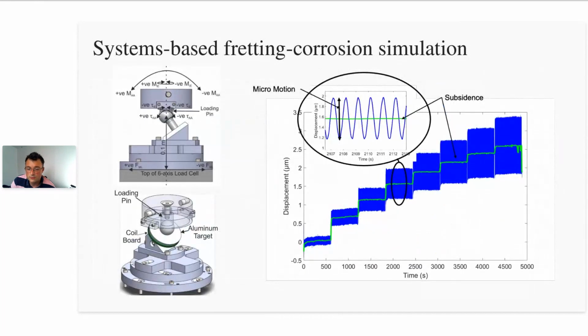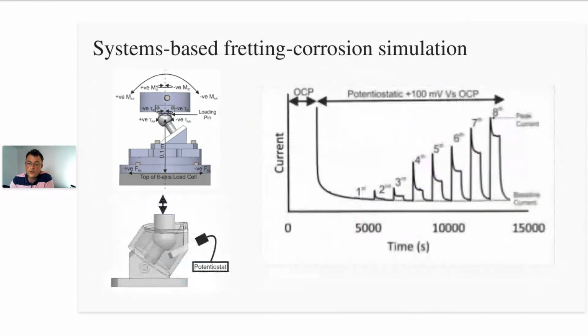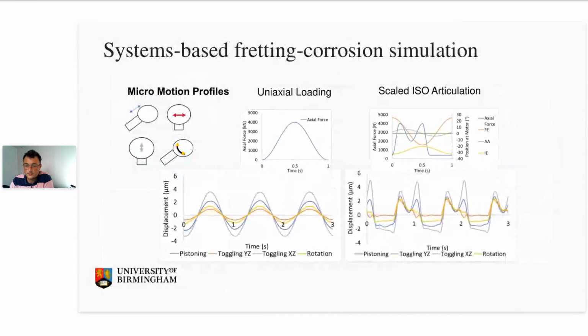But we can also then integrate sensors into here to then look at things like micromotion. So this is an eddy current-based micromotion sensing array where we can measure 3 points in the plane, look at toggling the micromotion. And also electrochemistry, and then ultimately merge the two together to give us information about what's happening at that interface, which you typically wouldn't get from standard ISO or ASTM-based testing.